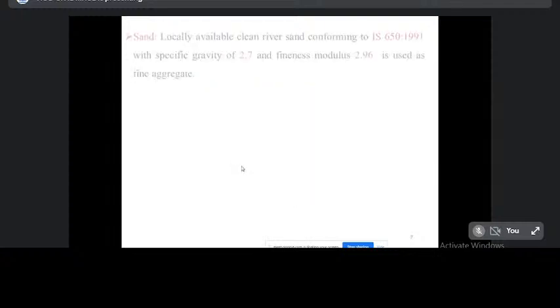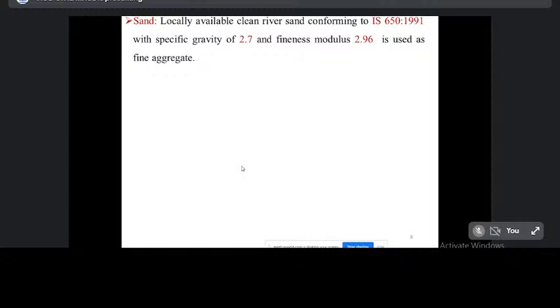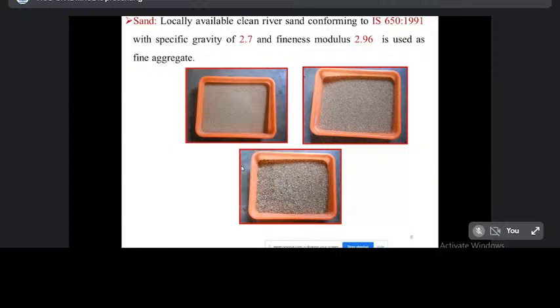Then the next material is sand. Locally available clean river sand conforming to IS 650-1991, with a specific gravity of 2.7 and a fineness modulus of 2.96, is used as fine aggregate. Here I have used 3 types of sand. It conforms to Ennore sand. That means sand passed through 2.36 mm and retained on 1.18 mm; then 1.18 mm passed and 700 micron retained; then 700 micron passed and 90 micron retained. Three varieties of sand: coarse, medium and fine. These 3 types of sand are used in this project as fine aggregate.